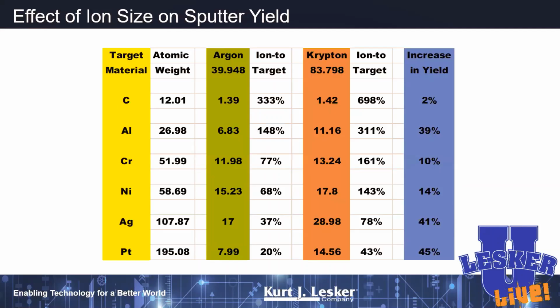Here's a bunch of different targets. We've got a carbon target, we've got aluminum, chrome, nickel, silver, platinum. They all have a variety of atomic masses here. Carbon's pretty light, platinum's a beast. And again, if you look at our argon atom coming in, at the ion to target atom ratios, argon's 3 times the mass of carbon, but for every 1 argon ion that hits carbon, we get about 1.4 carbons out.